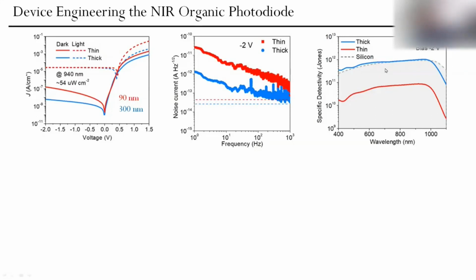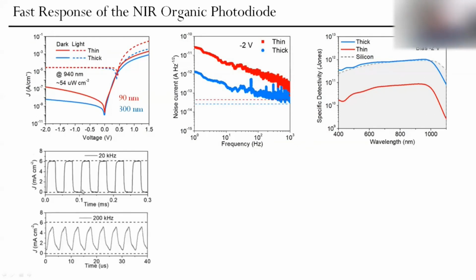And it's kind of a big achievement for a 300 nanometer thick piece of plastic, in comparison to 300 microns, so 0.3 millimeters, of single crystalline silicon. So that is quite a nice result, and specifically it works at long wavelengths, which is very interesting for medical applications.